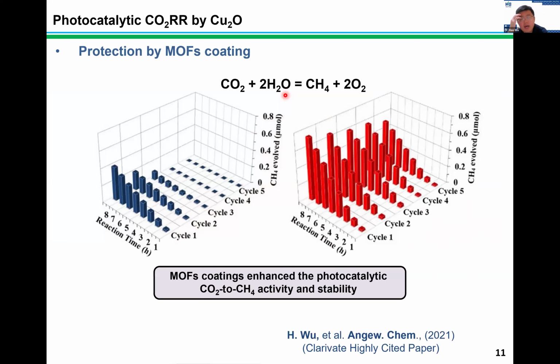Upon knowing that, we applied our catalyst in the carbon dioxide reduction reaction, and our results show that upon the MOF coating, the carbon dioxide to methane conversion activity is significantly increased, and more importantly, the stability is also improved. As for the bare cuprous oxide, after 3 cycles of experiments we almost lose all the activity in carbon dioxide reduction. On the other hand, with the MOF coating, we can retain around 75% of the original activity after 5 cycles of experiments.